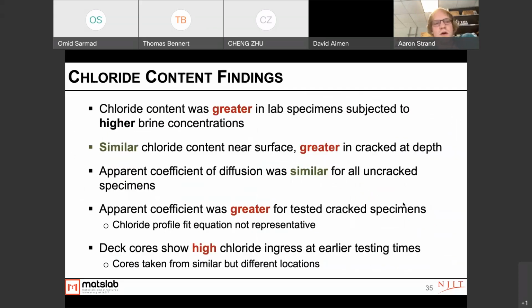So from our chloride content, we found that the chloride content was greater in lab specimens, especially when they're subjected to higher brine concentrations, and that a similar chloride content was found near the surface for the cracked and uncracked specimens, though this was greater in cracked at depth. And the coefficient of diffusion was similar for all uncracked specimens, and this makes sense as at the end of testing, none of them had shown any amount of corrosion at that point.